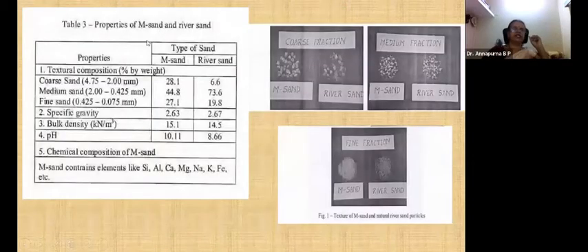Then properties of M sand and river sand. If you observe the M sand, coarse sand, 4.75 to 2 mm, we have 28.1 percent by weight, whereas river sand has 6.6. Medium sand from 2 to 0.425 mm is 44.8%, and here it is 73.6, which is higher. Finer sand here is 27.1, and here it is 19.8. Specific gravity here is 2.63 and 2.67, almost the same. Bulk density is 15.1 and 14.5. pH value is 10.1 and 8.66.